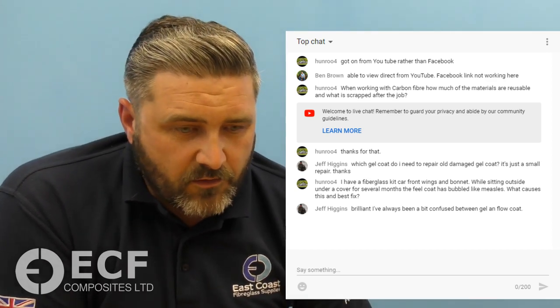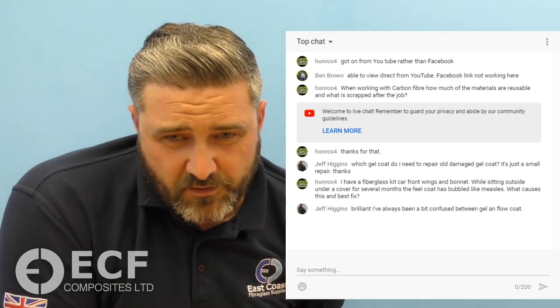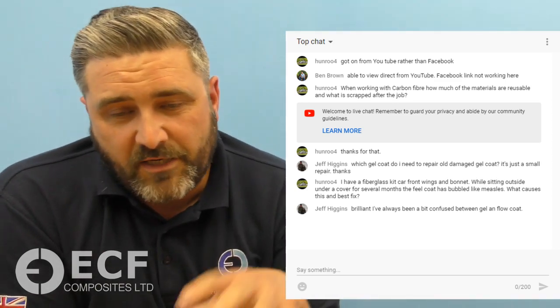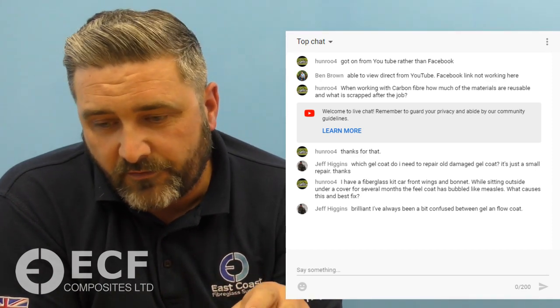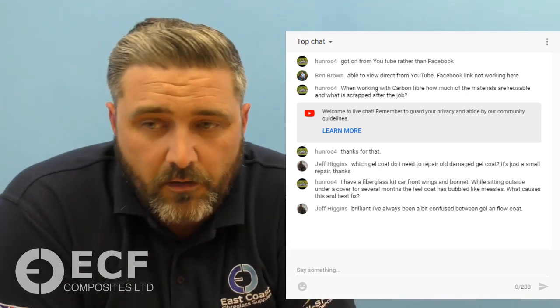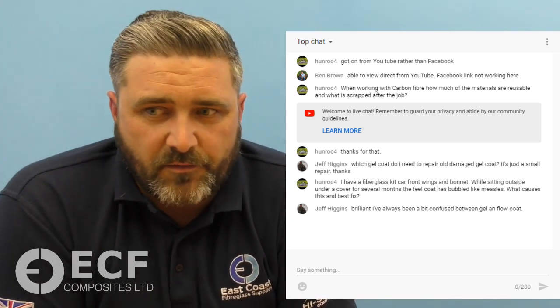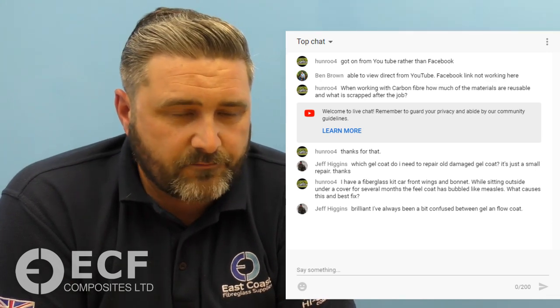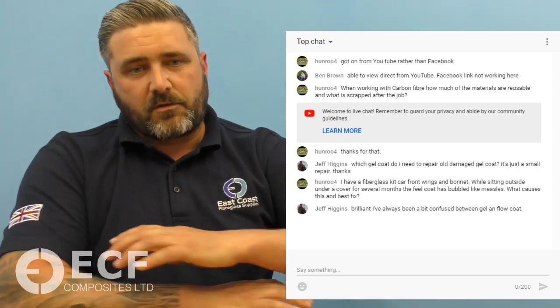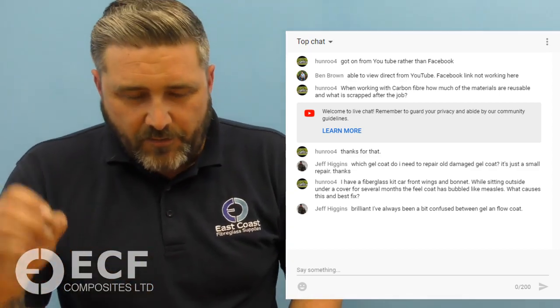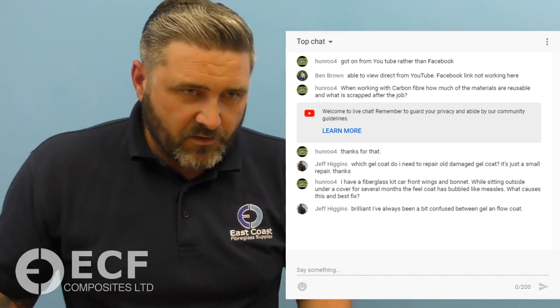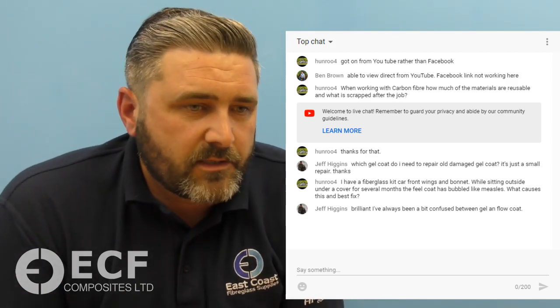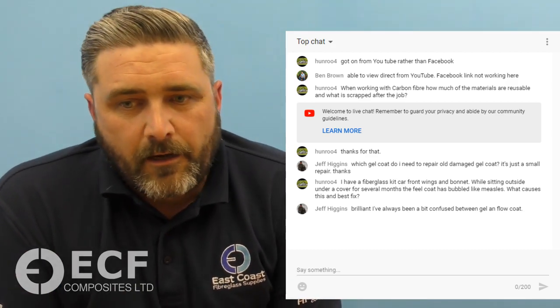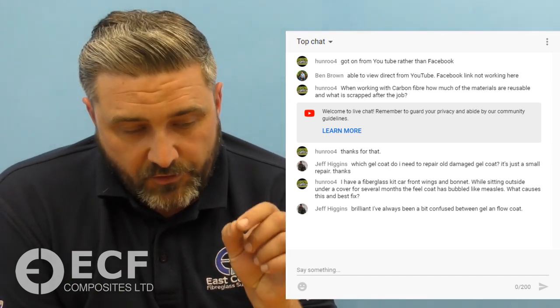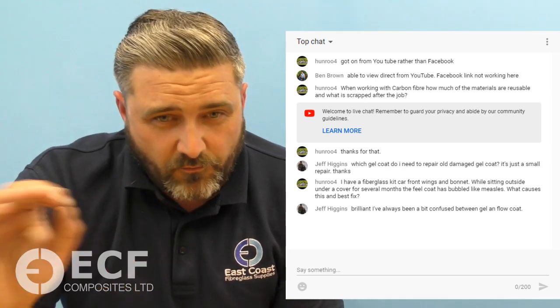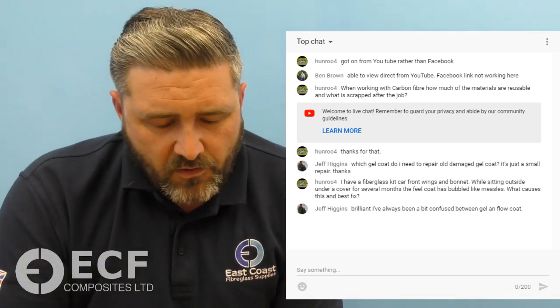Yeah, if it's standard fiberglass, it could be similar to what a lot of boats go through, known as osmosis, where the moisture's ingressed into the fibres, it's expanded under different temperatures, and it causes blisters on the surface. So you would probably treat that just the same way as we normally do with a boat. Break all the blisters, tap them all out. If the whole panel's absolutely covered in them, you don't want to be standing there just tapping them all out. So usually on boats they normally sandblast the surface just to sand it back and open up all those blisters. If it's not so extensive, you can just tap them out and fill them with gel coat and go through each one like that. It's a bit of an arduous task, but if it's not a big area, you can just do it that way.